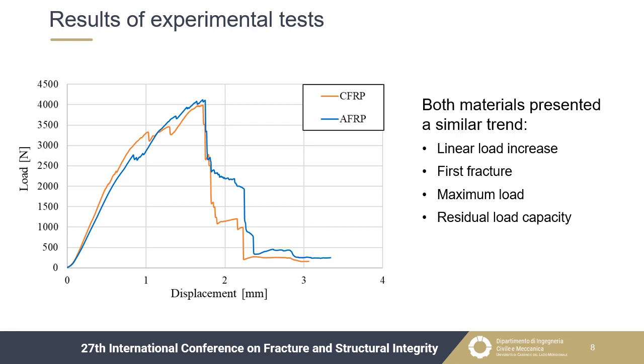As concerns the shape of the curves, a sudden load drop after the attainment of the maximum load can be observed. The increasing load section of the curves was characterized by an initial linear part, even if a slight deviation from the linearity can be noted, followed by a first minor load drop, probably due to the breakage of some fibers. The subsequent part showed a nonlinear load increase with other load drops. Also in this case, this trend is caused by the breakage of more fibers.